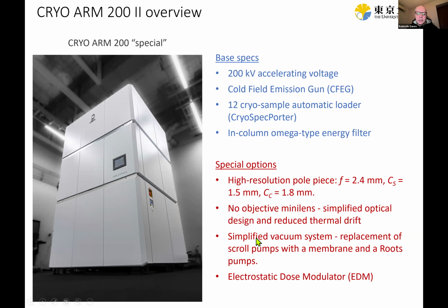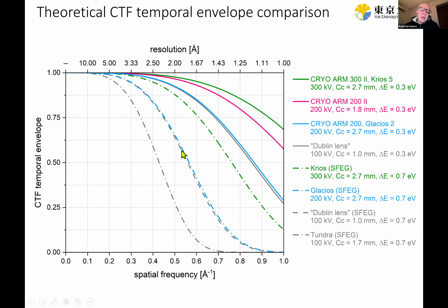And by removing this lens, they optimized the overall performance. Also, the vacuum system was simplified, so smaller and quieter pumps, requiring less service. And finally, an electrostatic dose modulator, which is a very fast electrostatic shutter, which can be used both as an electrostatic shutter and as a beam intensity modulator by applying a modulating frequency which is much higher than the frame rate of the detector. So the basic optical performance of the microscope is determined by the contrast transfer function temporal coherence envelope.